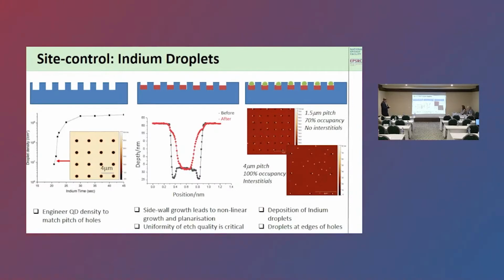So what kind of results do we get when we try this? The first thing is in terms of fabricating the structure. As I mentioned earlier, through the droplet epitaxy process we have independent control of a number of parameters of the dots. In particular, using the indium time, we can control the density of the dots from around 10 to the 7 up to 10 to the 9 or so.